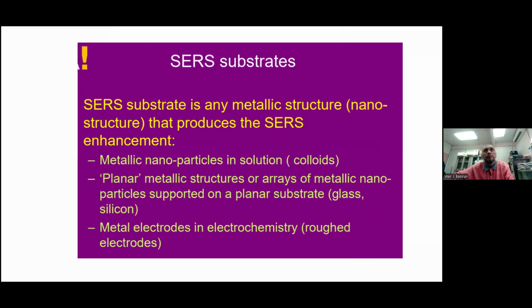Okay, so the SERS substrate can be any metallic structure that produces SERS, as long as it is a metal, for example gold, silver, platinum. It must have a metal surface with plasmonic wave, meaning that the electron will not interact with the oxygen in the atmosphere or the moisture in the atmosphere. It is a free electron which oscillates on the surface of the metal. So then you have the plasmonic resonance. And this plasmonic resonance is very critical for the electromagnetic enhancement in the Raman SERS. So, for example, the substrate can be nanoparticle solution, planar metallic structures, and metal electrochemistry, as long as you have the plasmonic wave on that metal surface.